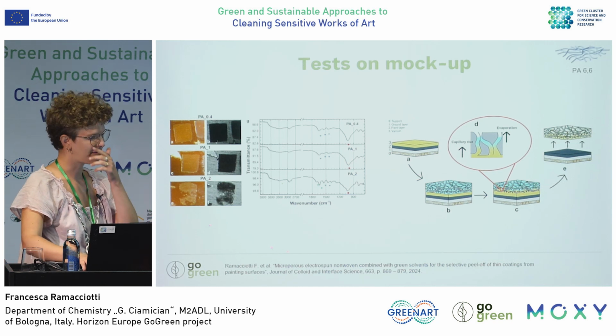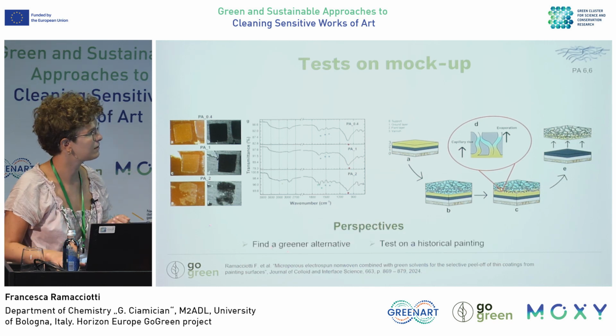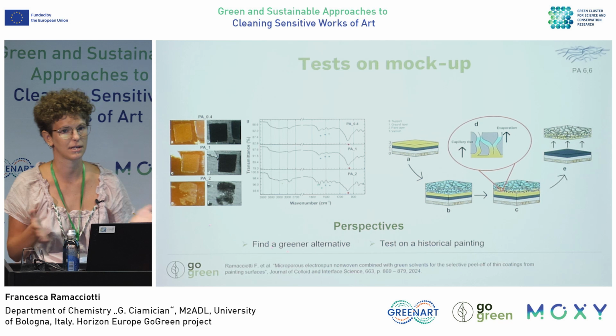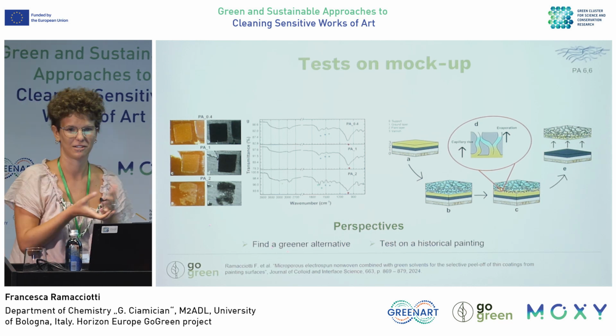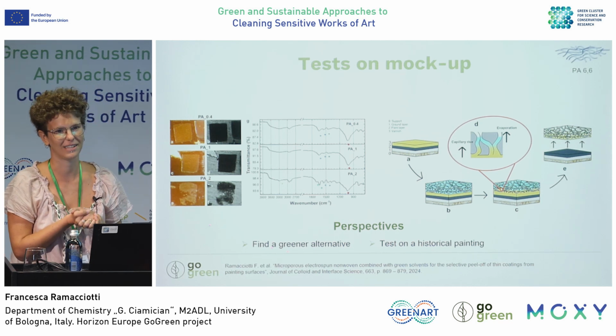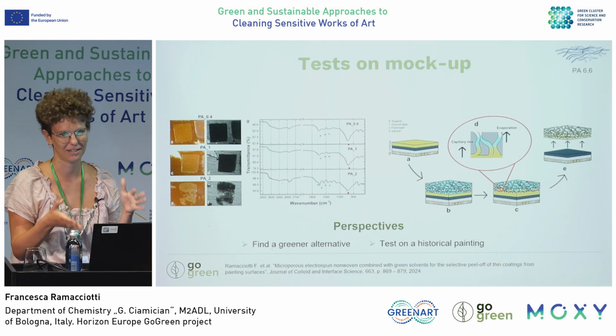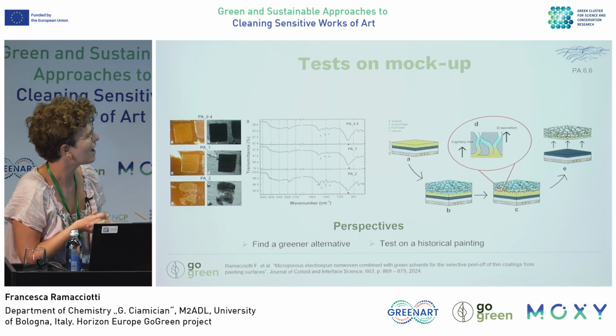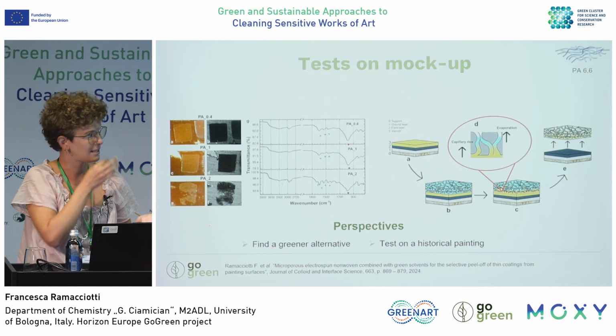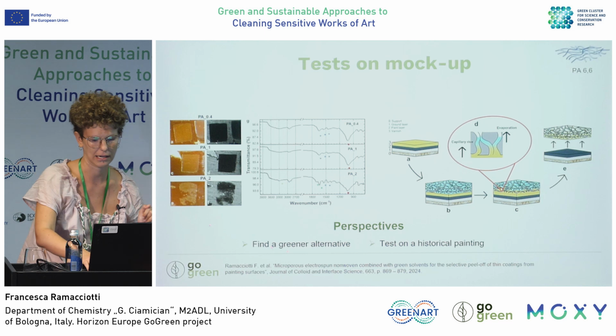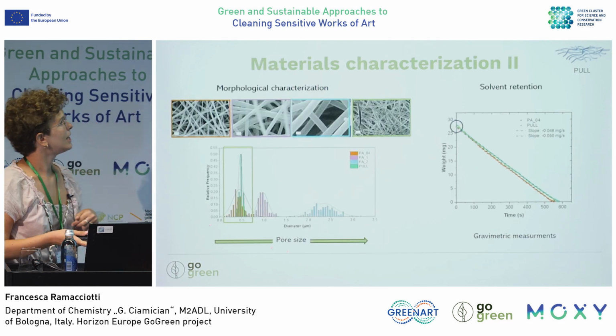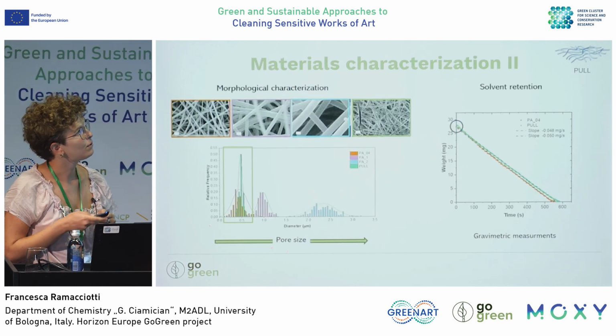So we were left after this with two main perspectives. First, finding a greener alternative, because as I said, polyamide 6,6 is not green, and also the solvent that I use to produce the mat is not green, and it's really toxic. And also testing these materials on a historical case. So the alternative that we found is pullulan.